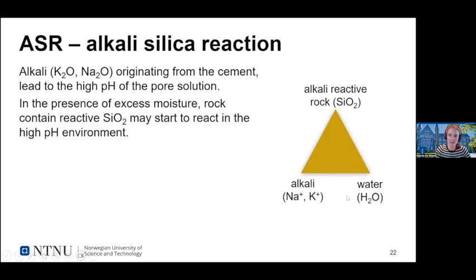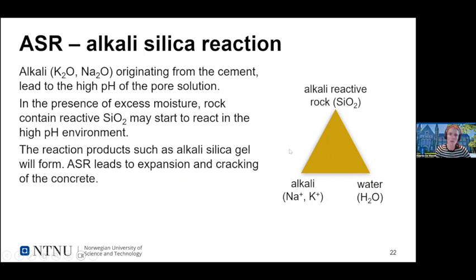We need the presence of excess moisture, water, and a reactive rock containing reactive silica. And reactive rock will react in the high pH environment and with the additional water to form reaction products such as alkali silica gel. And ASR leads to expansion and cracking of the concrete. It's a slow reaction, but we have quite some trouble with it here in Norway. But where do SCMs come into play here?